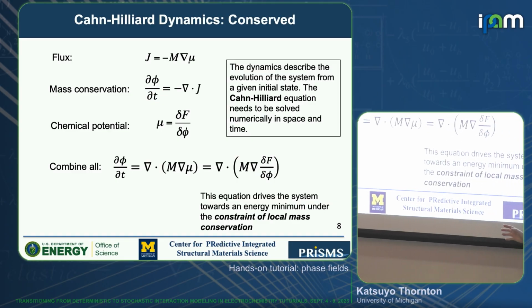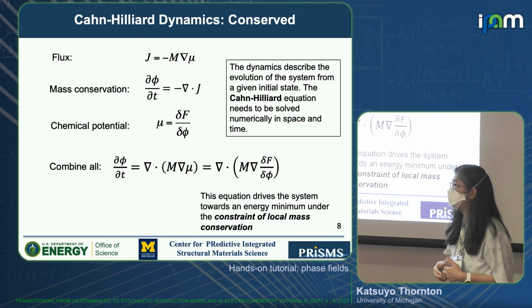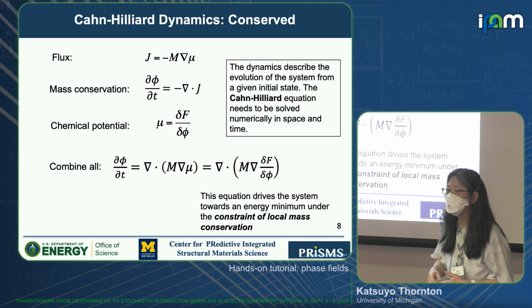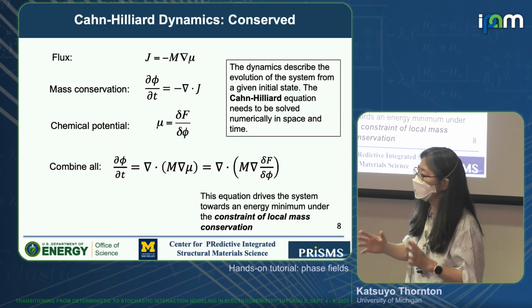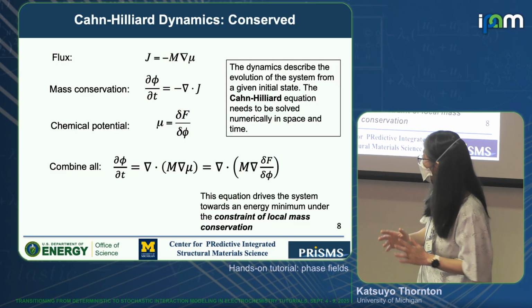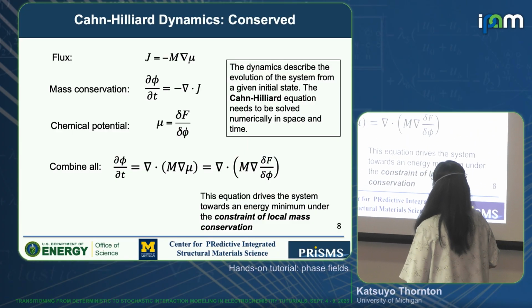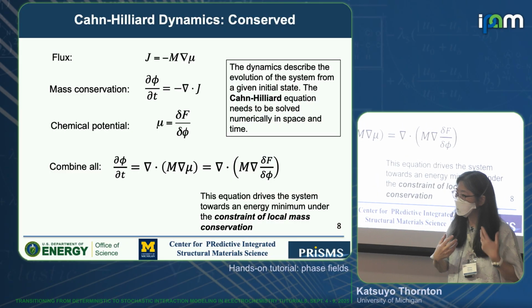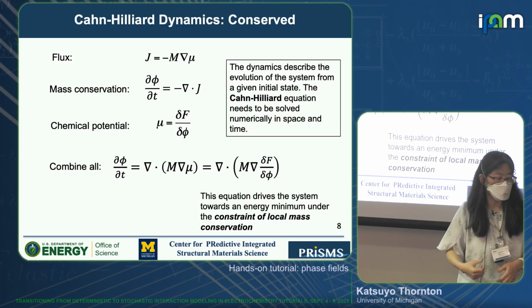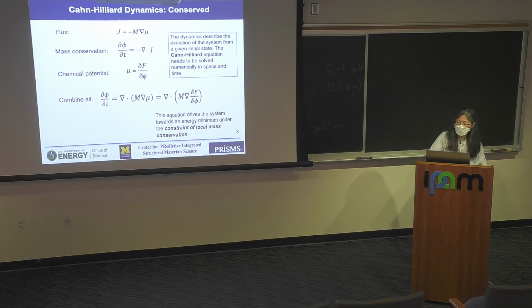And this is the classical Cahn-Hilliard equation and describes spinodal decomposition. If you start the system with concentration within the spinodal region, and then if you start out with some other range, you'd have a nucleation and growth that would be reproduced by solving this equation. Another type of equation, I mentioned there's a conserved, right? So this is a conserved case.